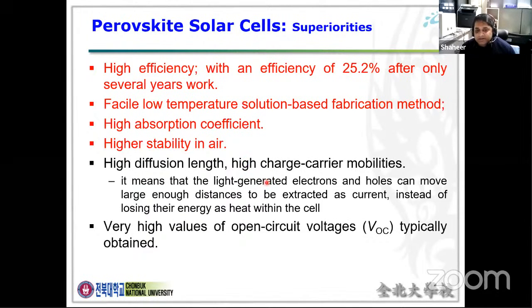So let's conclude why perovskite solar cells are superior in the area of thin film solar cells. The first reason is its high efficiency, over 25.2%. Another is that we can easily manufacture them using a facile low temperature solution based fabrication method. Also, the perovskite materials show a high absorption coefficient, and these solar cells are highly stable in air. And the interesting thing is that perovskite solar cells show a high open circuit voltage, over 1.1 volt, which is much higher than the silicon solar cell open circuit voltage.